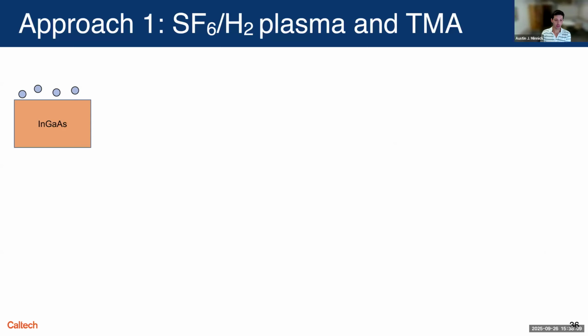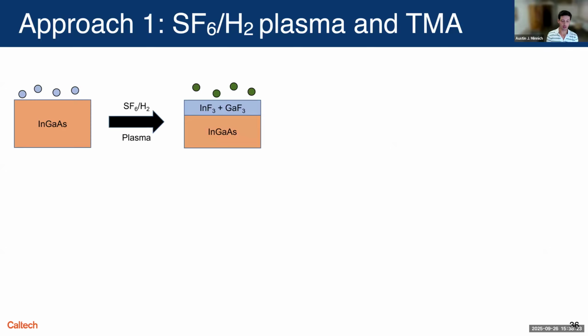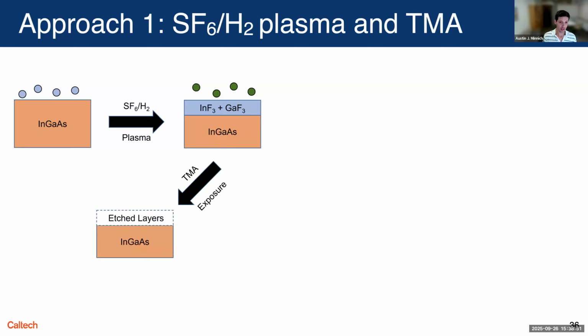So we decided to try to advance the chemistry side of things by creating an ALE process for indium gallium arsenide. The first approach is where we tried to kind of mimic the thermal ALE process I showed you, but using a plasma mixture. The justification is that HF is typically not usable in many commercial tools because of toxicity. When you combine SF6 and H2 in a plasma mixture, you actually make HF in the reactor, and you don't need a source of HF, which is kind of interesting. So we did that, and we produced these fluorides. Then we exposed to TMA, which is based on other related etch processes that have been found. And you can repeat that.